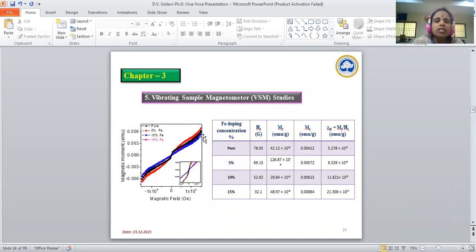This slide shows vibrating sample magnetometer results of synthesized nanoparticles. Generally, the pure cadmium selenide nanoparticles exhibit diamagnetism with a negative susceptibility value, but with doping it cannot remain diamagnetic. They exhibit either paramagnetic or ferromagnetic behavior. As a result, the saturation magnetization values increase with increase of Fe metal doped into the cadmium selenide nanoparticles. This result is in agreement with the already reported work.